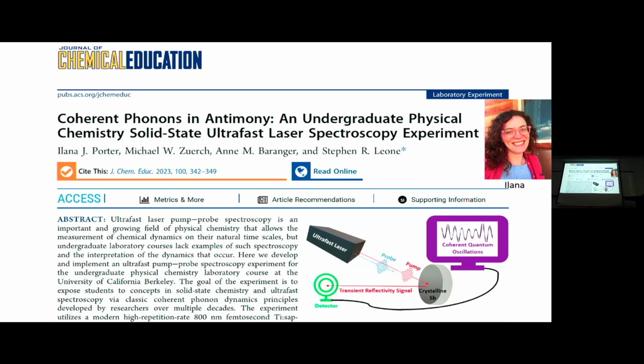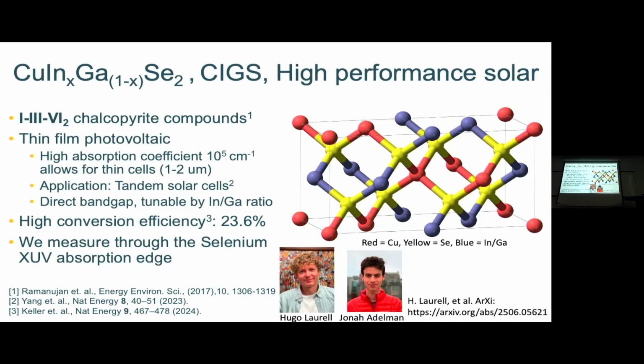It is much too difficult to bring an attosecond laser into an undergraduate laboratory, but by pump probe reflection, you can easily measure the coherent phonons in a material like antimony. So now our undergraduate students perform this experiment. They learn about pump probe, they learn about correlation, and they learn about coherent phonon and the different mechanisms of coherent phonon. And Alana, who's now on the faculty at Reno, was the one who heroically made this work for a very small amount of money in our laboratory, and it now is part of the routine that we operate in that lab.